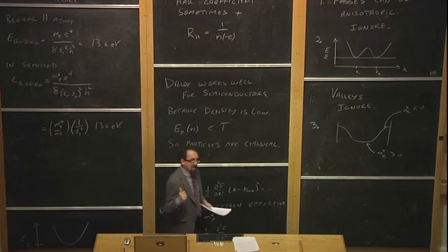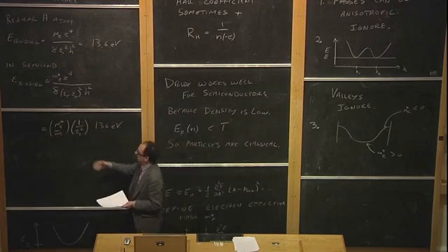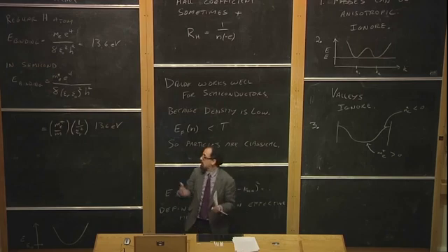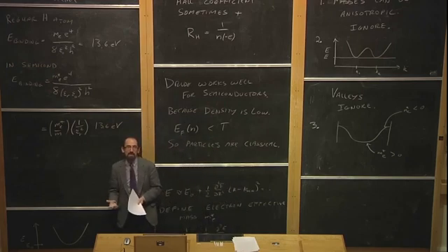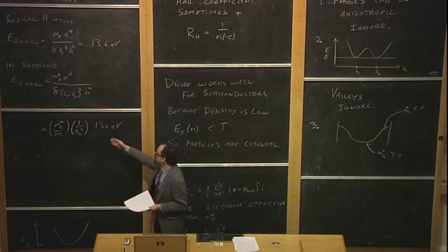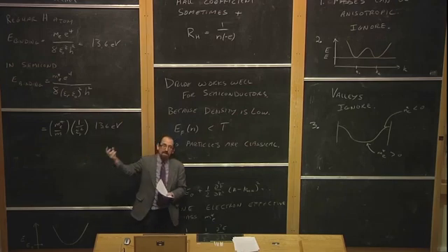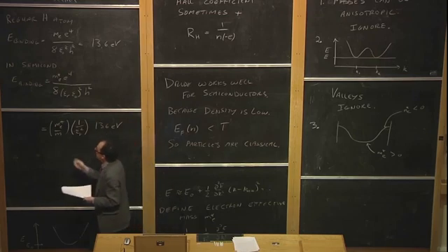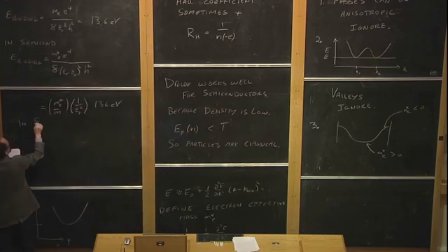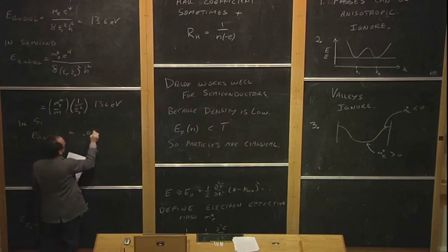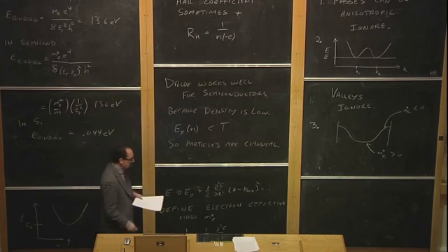Now, this expression can be a whole lot different from 13.6 eV, and generically it's going to be a lot smaller. Typically, effective masses of electrons in semiconductors can be 1/3 of the mass of an electron. It can be even 1/10 of the mass of an electron, or even smaller. The dielectric constant in semiconductors can be numbers like 10. So that means that the actual binding energy of the electron to the proton in the semiconductor can be as much as a factor of 1,000 less than this. For example, in silicon, E binding of the electron back to its dopant nucleus is 0.044 electron volts, a much, much, much smaller number.